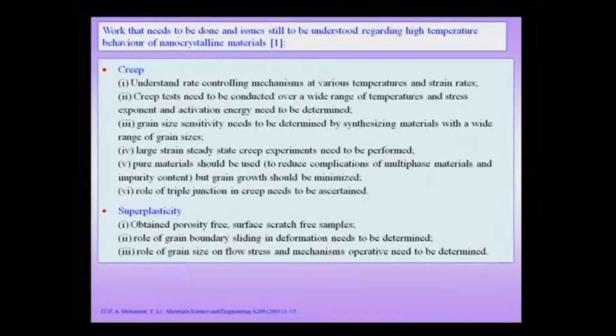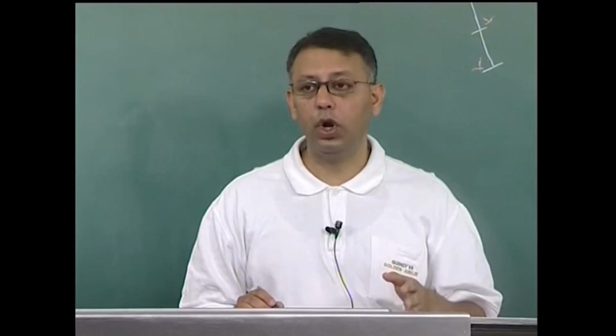or fewer parameters of understanding. In the case of creep, the rate control mechanism at various temperatures and strain rates needs to be understood. Creep tests need to be conducted over a wide range of temperature and stress, and the stress exponent and activation energy need to be determined. Grain size sensitivity needs to be determined by synthesizing materials with a wide range of grain sizes. It is a very challenging problem, and when we talk about a wide range of grain sizes, we are talking about close to monodisperse grain size.